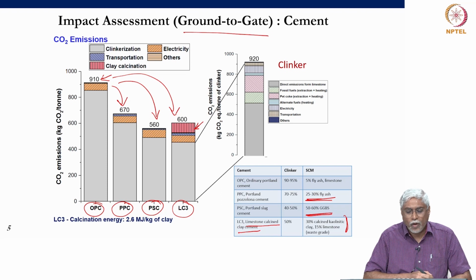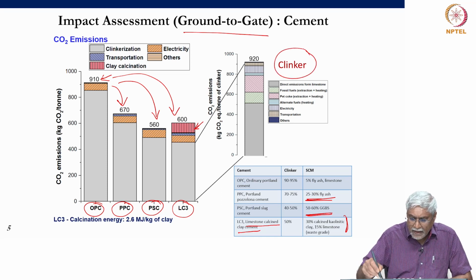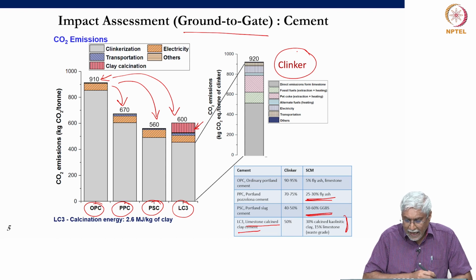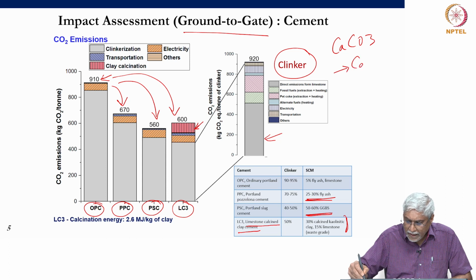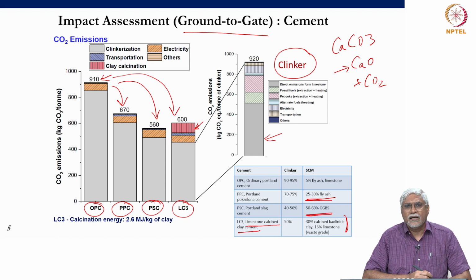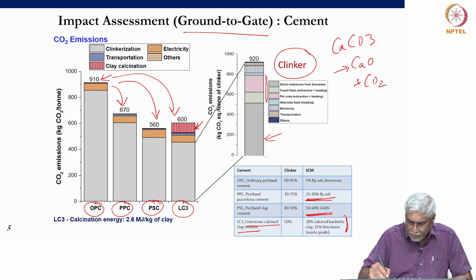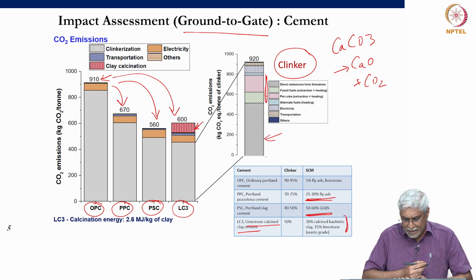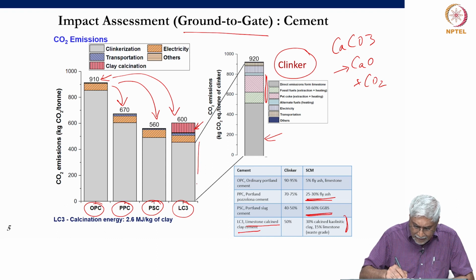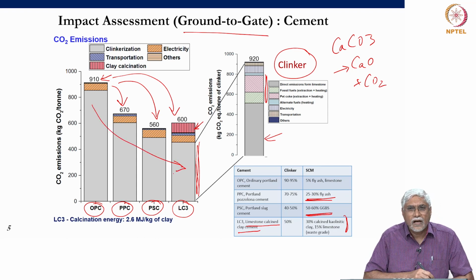So, what we find is the main culprit in having a high carbon footprint of cement is the clinker. And in the clinker, most of the carbon footprint is from the limestone, because calcium carbonate converts to calcium oxide and CO2. So, anytime we convert limestone into calcium oxide, we are going to give out CO2. Other than that, we have the fuels. The fuels are being burnt because we have to heat the material to 1500 degrees in the kiln, and this is going to emit CO2. In this case, pet coke and other fossil fuels are used. The grey part of each of these bars is clinker, and we see that as we decrease the clinker, we are going to reduce the carbon footprint.